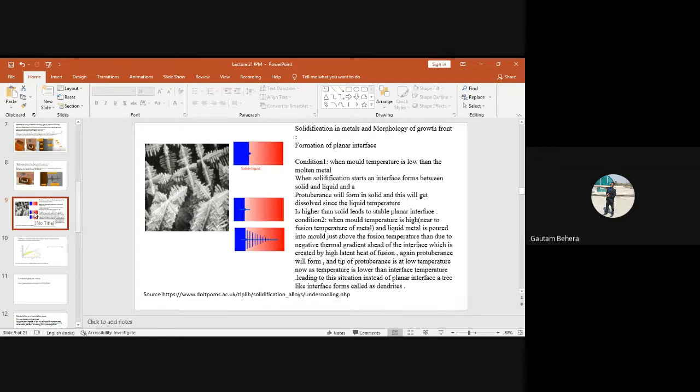The main hint I have given is the concentration of solute. You want to make an alloy, and finally you want the alloying elements to be uniformly distributed everywhere upon solidification, right? But when a dendrite is forming, there is preferential growth in particular directions, and due to this, dendritic arms and interdendritic regions form, where liquid is still there. This liquid will finally solidify, and all the solute will get rejected by the dendrites into the interdendritic regions, and this is the last liquid to solidify. So are dendritic structures good for our properties or bad for our properties?